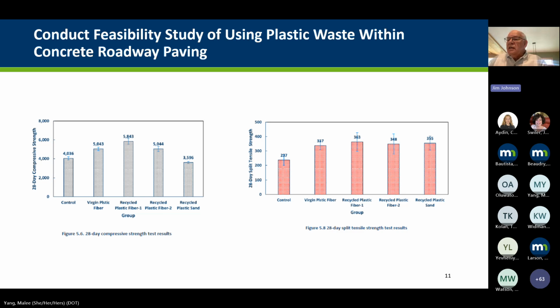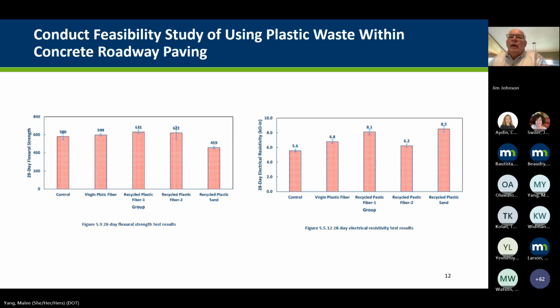Continuing with the different types of testing that were being performed on these five different mixes. On the left here, you see the 28-day compressive strength test results. And then on the right, the 28-day tensile strength test results. Next page, please, Maylene. Continuing, on the left, you see the 28-day flexural strength test results. And on the right, the 28-day electrical resistivity tests, which I know nothing about. Again, we'll have to refer to Tom for his expertise as to what those are. Next slide, if you would, please, Maylene.